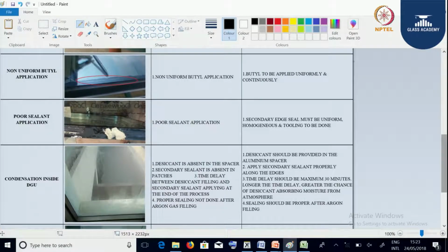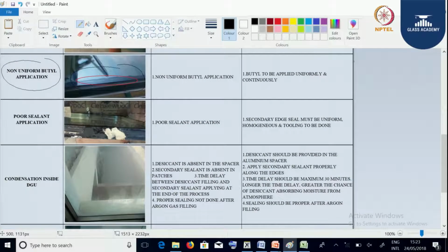Next one is the non-uniform butyl application. You can see in the figure the butyl is like a zigzag line. Always the butyl should be straight and continuous, as it acts as a moisture barrier. This is due to non-uniform butyl application, and we can overcome this issue by applying butyl uniformly and continuously.